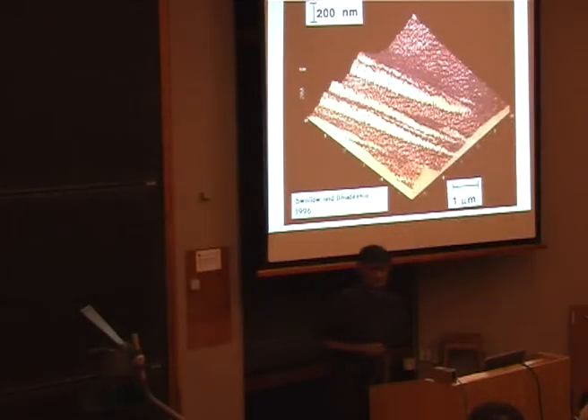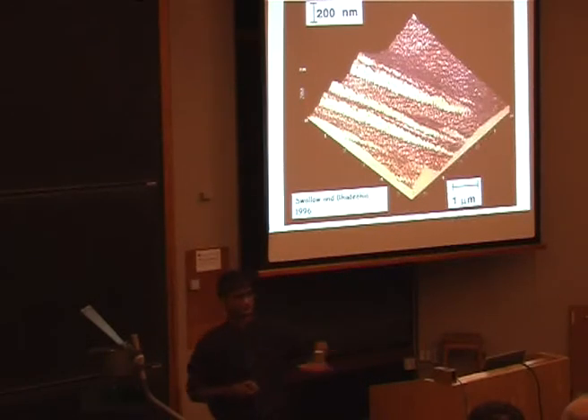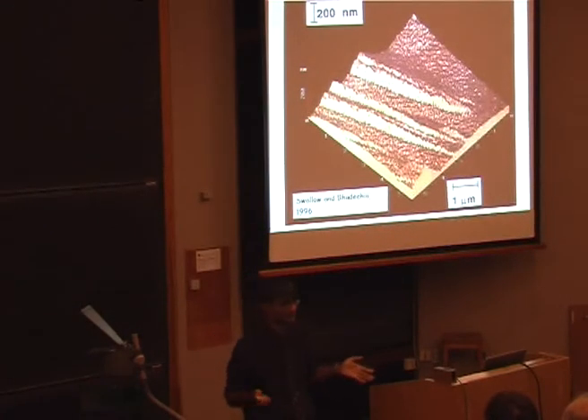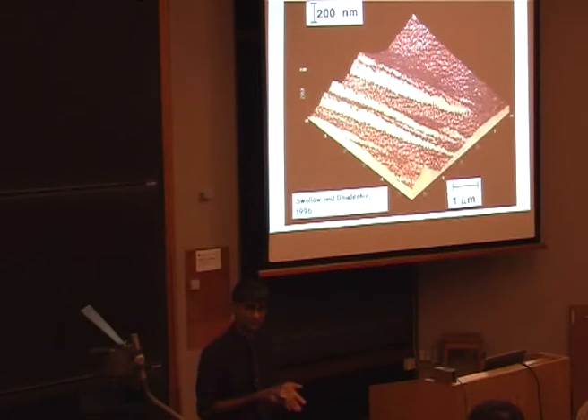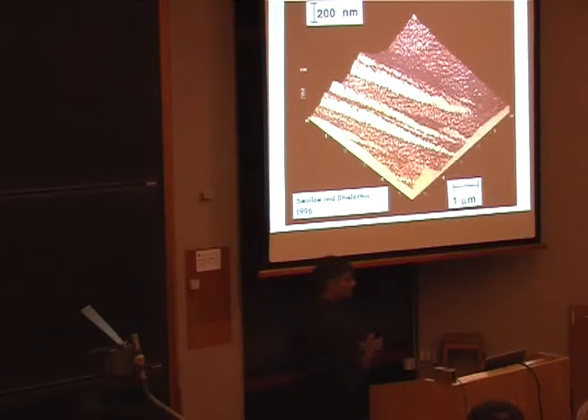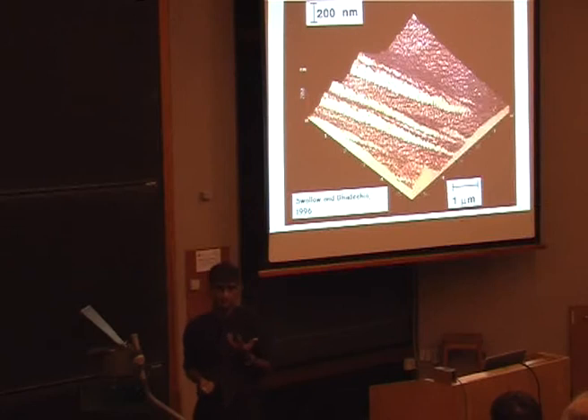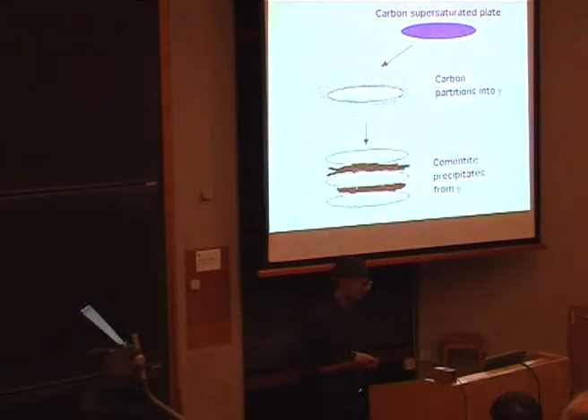Well, this is a displacive transformation. You take a crystal of austenite and you allow it to transform to bainite by a deformation rather than diffusion. And you can see that there are some very severe changes in shape produced by the phase change. Now imagine that these changes in shape happen with the crystal surrounded by thousands of other crystals. That's going to cause an enormous amount of strain energy. And the equation for that strain energy was first derived by Jack Christian in 1956 in this department. Okay? So that amounts to something like 700 joules per mole of stored energy, a huge term. So why not exploit this as a mechanism of storing energy inside the material?